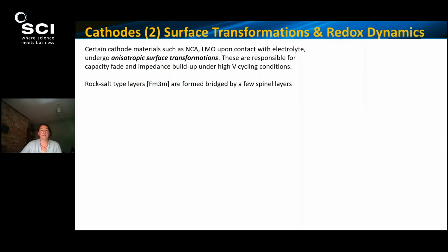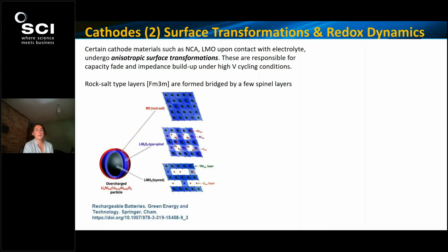Certain cathode chemistries, such as nickel, cobalt, aluminium, and lithium manganese oxide, upon contact with the electrolyte, can also undergo deleterious surface transformations, which will seriously influence how well and how quickly lithium can diffuse. And this is especially problematic at higher voltage cycling conditions, where the higher capacity cathode materials need to operate efficiently. So in such surface transformations, we can see a transformation from the classic layered type structures through spinel bridging phases to a rock salt type crystalline structure, which you can see in this image on the bottom left.